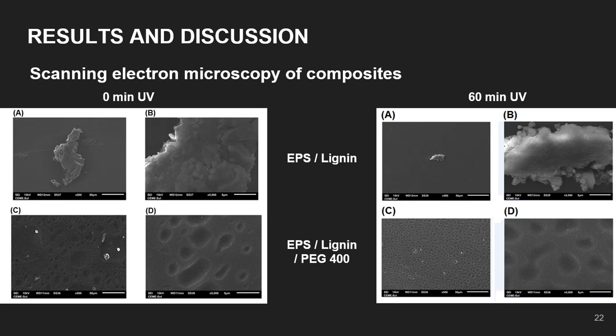From the micrographs on the present slide, it is possible to observe more closely the effect of the photochemical treatment on the surface of the composites, where in Figures A and B, the composites of EPS and lignin are observed with magnifications of 500 and 5000 times, and in Figures C and D, the composites with EPS, lignin, and polyethylene glycol incorporated, also with magnifications of 500 and 5000 times. Apparently, exposure to UV light promotes a smoother surface with a less rough interface between reinforcement and matrix, which is indicative of a more homogeneous dispersion through the composites.